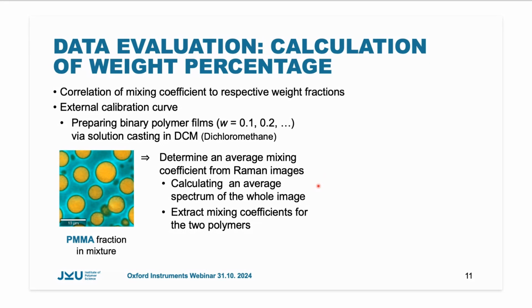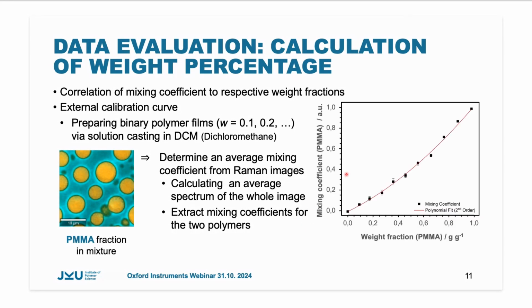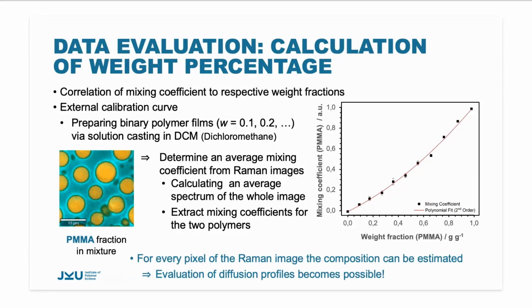which now contains a known amount of the two polymers. And then with this knowledge, we can extract the mixing coefficient for the two polymers when we just have the one mixing coefficient for one component and we have the known weight fraction. We did this for PMMA and SAN, and then for every pixel of a Raman image, the composition can be determined, and this allows us now to evaluate diffusion profiles.